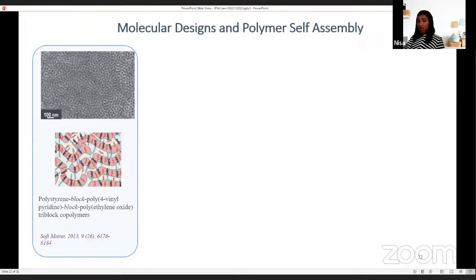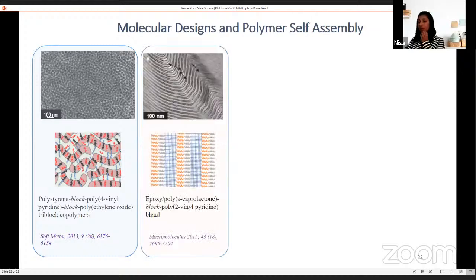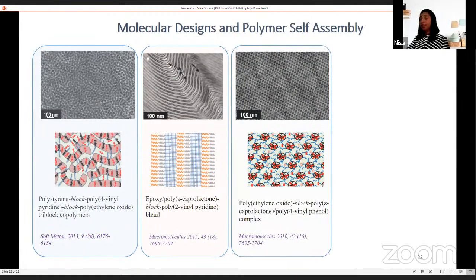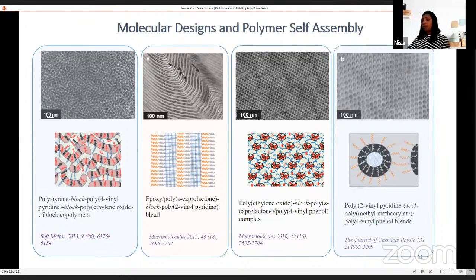In this study, we created rod-like features with hexagonal patterns from a triblock polymer. This work shows formation of an ordered lamellar structure. The orange and blue color representation denotes the organization of different polymer chains. Here you can see some hexagonal arrays of nanostructures with size around 30 nanometers. Here we used a double crystalline block polymer blended with a homopolymer system. The last one is showing hexagonal cylindrical arrays of polymer chains.